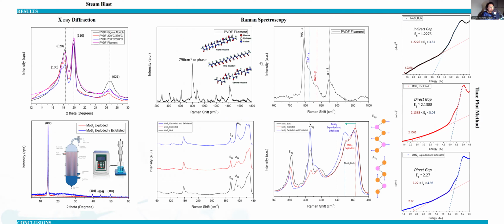So we have confirmed the presence of alpha phase, which has no piezoelectric properties, but we know from different research groups and articles that we can induce the beta or gamma phases with the incorporation of molybdenum disulfide. So we want to incorporate our molybdenum disulfide, already exfoliated with our two-step process, and with this incorporation we could have improved and enhanced the piezoelectric properties of the PVDF.